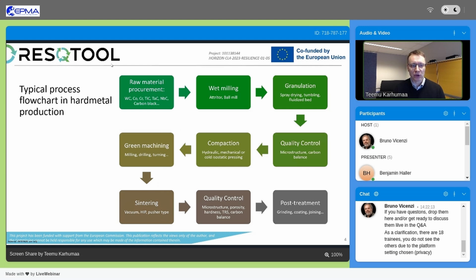We start with raw material procurement, the tungsten carbide and cobalt, and then other elements which are sometimes needed are mixed and milled in an attritor or a ball mill. The slurry is granulated, or dried and granulated, to a free-flowing powder. Then there is typically a quality control step in this phase.